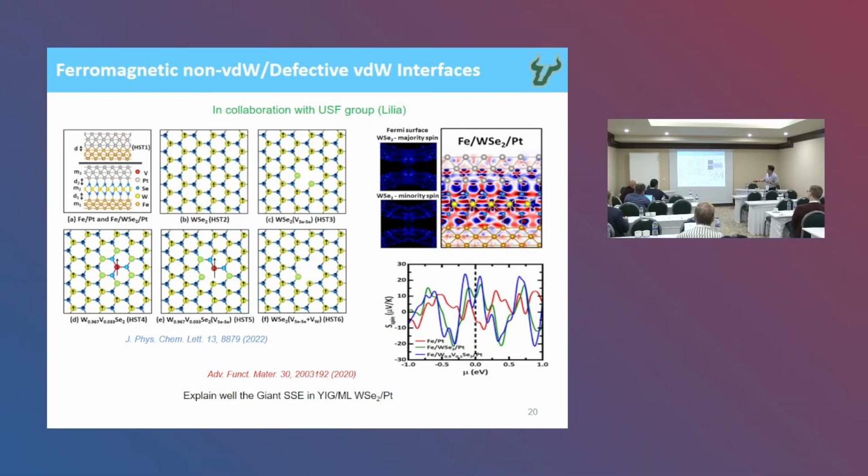So we see that this really changes how the magnetic substrate induces a magnetic moment on the monolayer. In the pristine case, we see it is ferromagnetic. But when you dope vanadium, we see the vanadium magnetic moment and the nearest spin at the tungsten site are anti-ferromagnetically coupled, which is consistent with what we observed before for vanadium-doped tungsten diselenide monolayer.